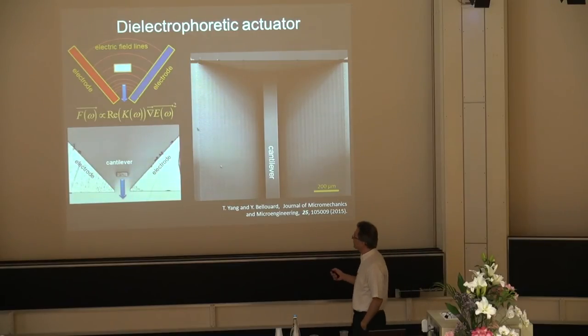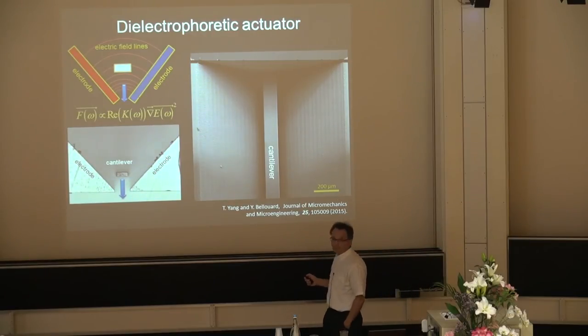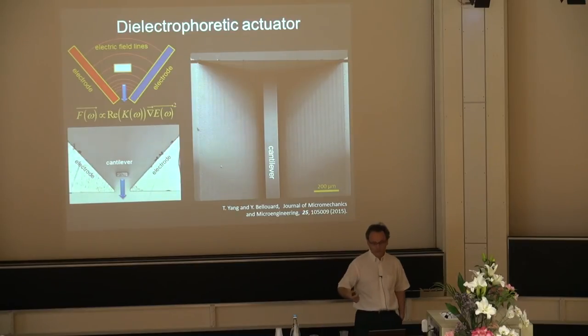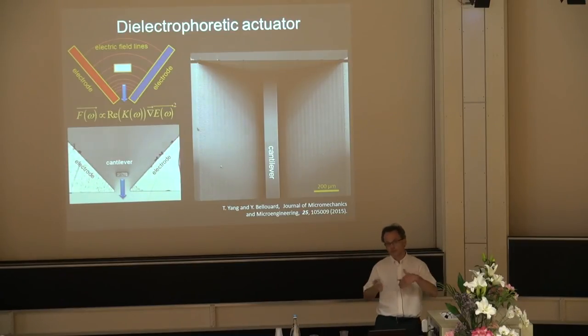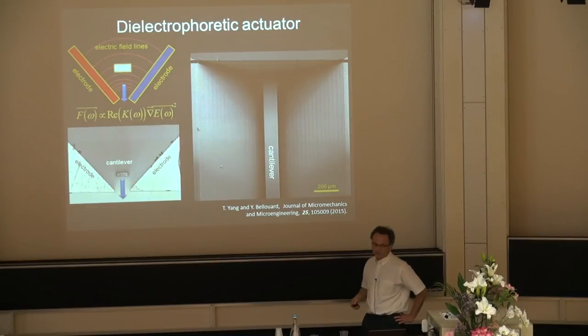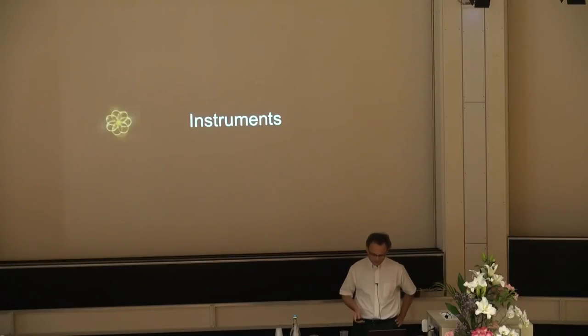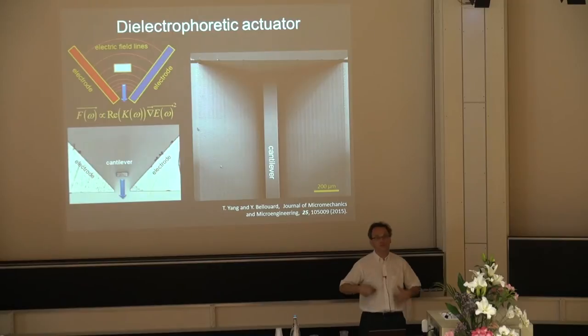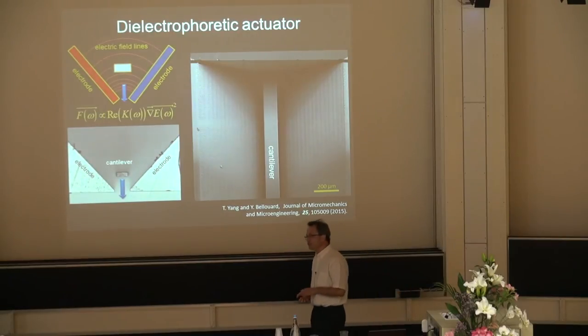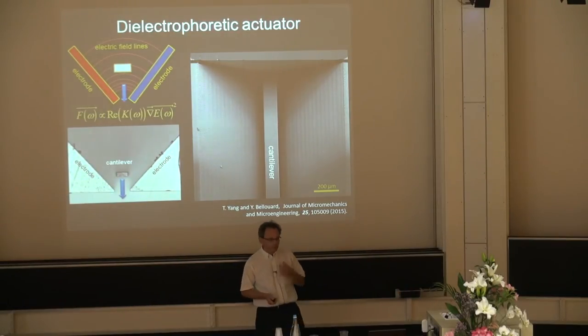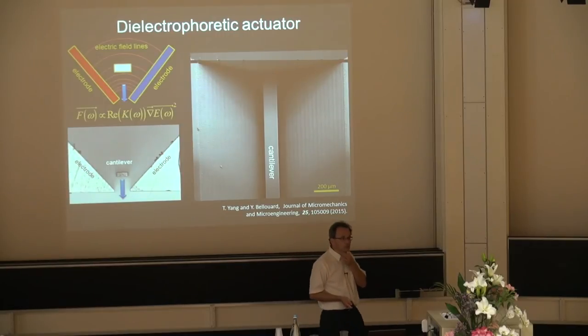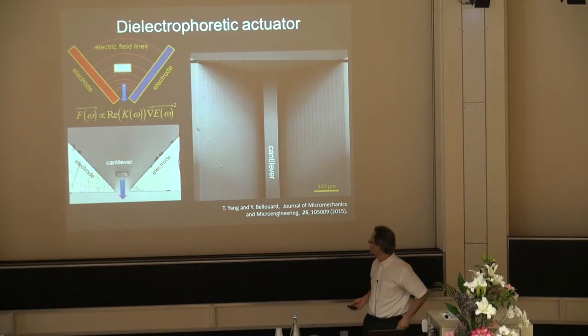That's a second order effect. So you need to have a gradient of electrostatic field, and that depends on the square of it. So it doesn't matter if I switch signs from electrodes, for instance. And then furthermore, that can be positive or negative because this will depend on these parameters, which depend on the material itself. Okay, but just to show you an illustration that because we can do 3D devices, now we can also explore how to make things we could not test before, like these kinds of things.